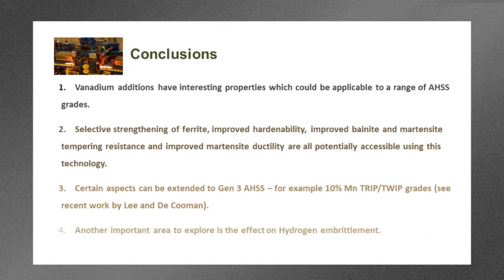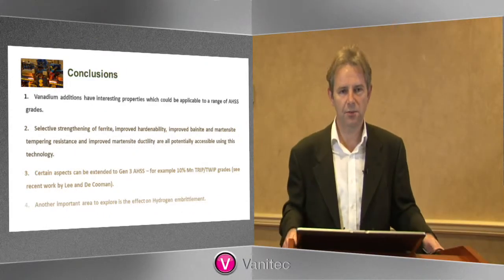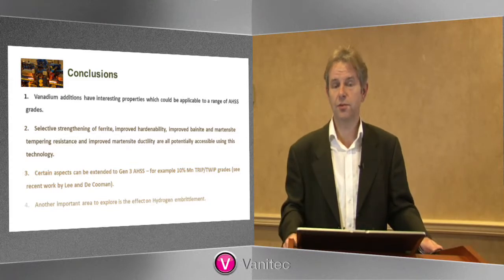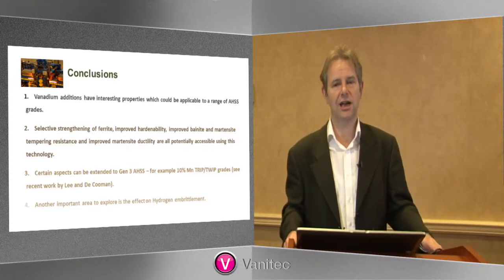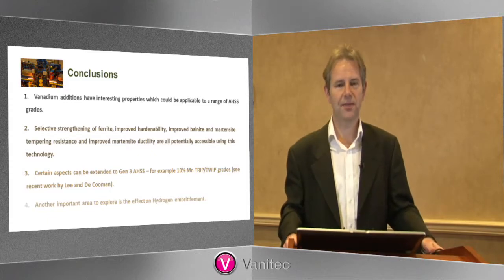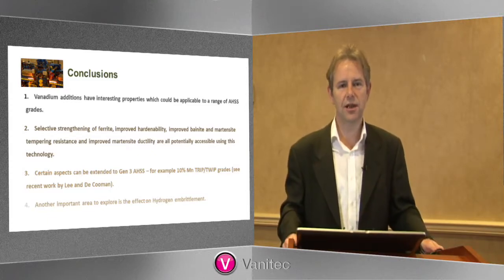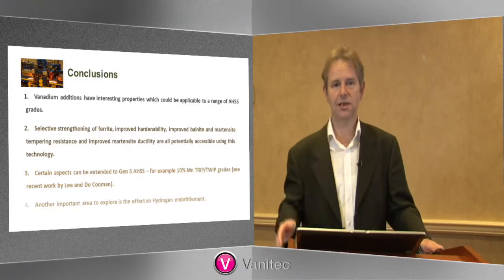So what I'd say is that vanadium additions have very interesting properties, and they could be applicable to a very wide range of advanced high-strength steel grades. Some of the things that you can do with vanadium include selective strengthening of ferrite if you have multi-phase steels with intercritical annealing steps involved in the production. You have improved hardenability, which is something I haven't been able to talk about. You have improved bainite and martensite tempering resistance and improved martensite ductility. Those are other factors which I haven't been able to touch on in this talk due to time constraints, but they're all potentially accessible using vanadium technology.